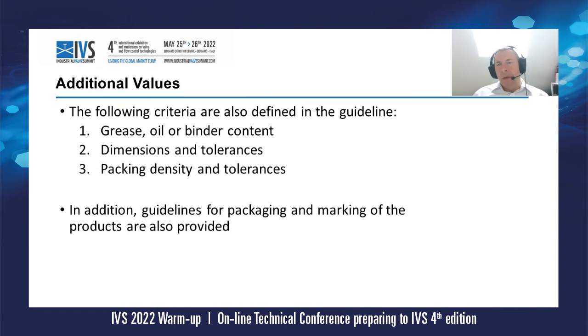Besides the specific values that have been shown in the previous slides, other criteria are also defined in the guideline. For example, for the pump packings, again, the grease, oil or binder content, because this shouldn't be too high, because again, a high amount of grease, oil and binder will give quite high creep relaxation or volume loss, and the packing won't last that long in the application.